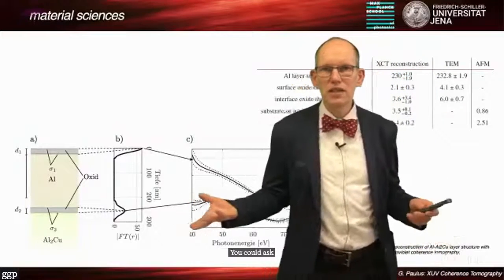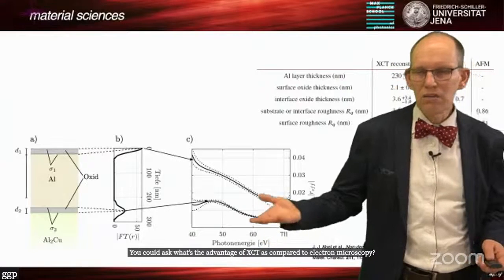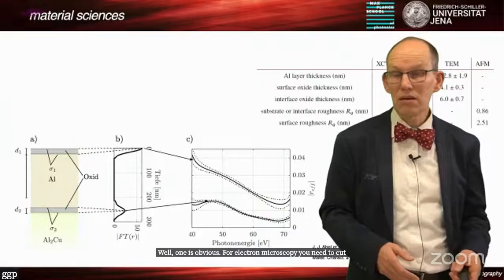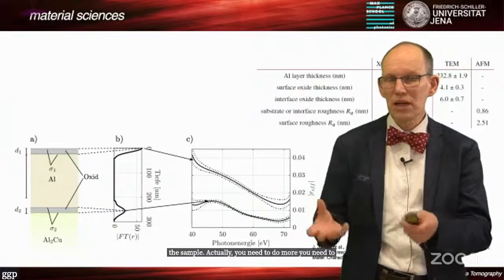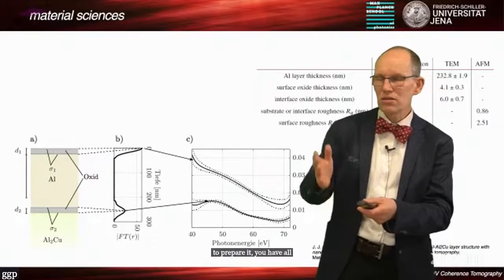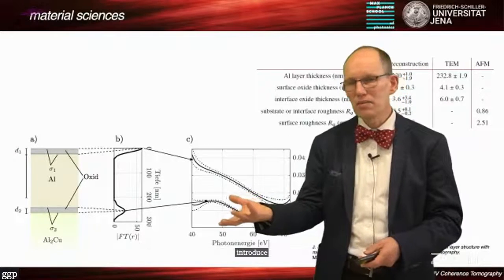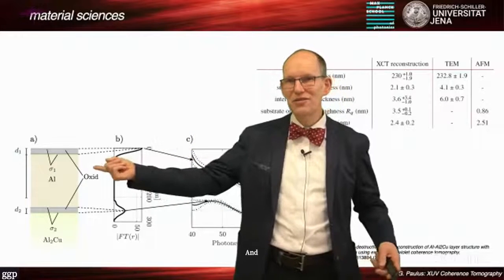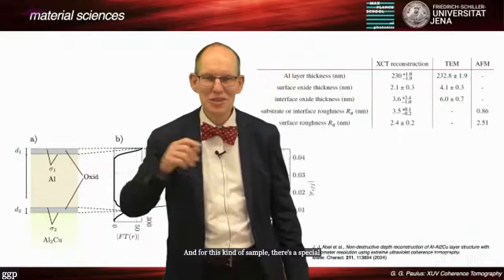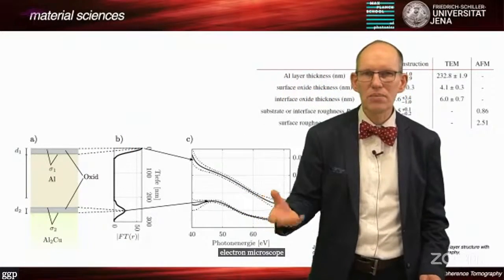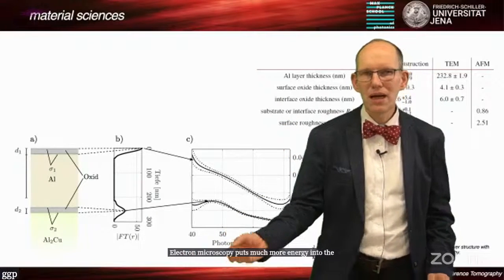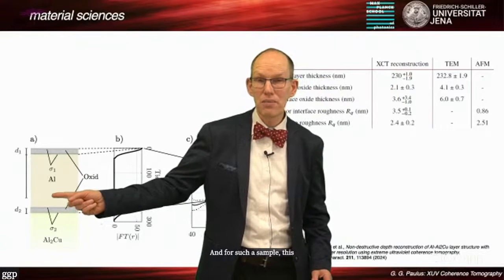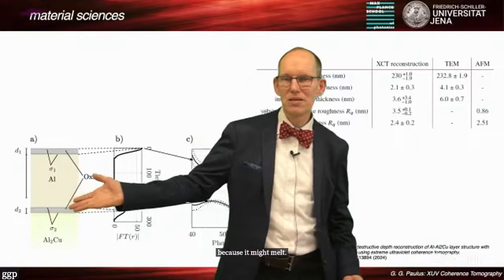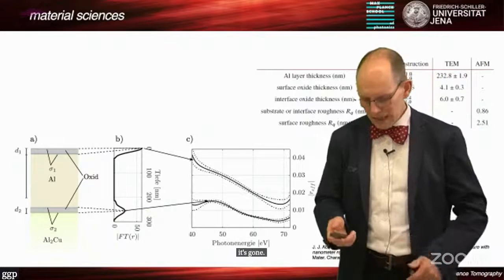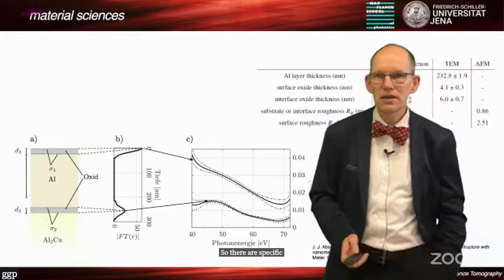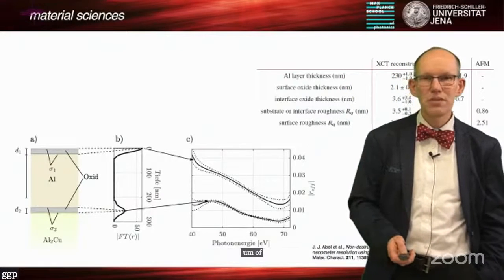You could ask, what's the advantage of XCT as compared to electron microscopy? Well, one is obvious. For electron microscopy, you need to cut the sample. Actually, you need to do more. You need to prepare it. From the cutting process, you typically introduce gallium. And for this kind of sample, there's a special problem that was also a surprise to us. Electron microscopy puts much more energy into the sample than we do. And for such a sample, this is particularly problematic because it might melt, right? And then the sample is gone. So there are specific and significant advantages of imaging using XUV.